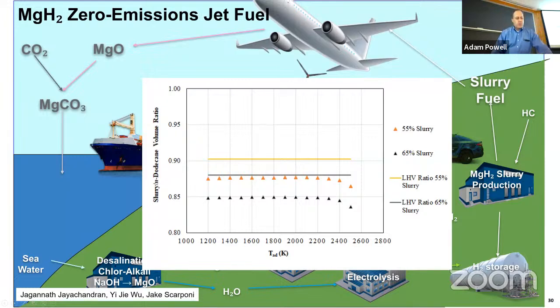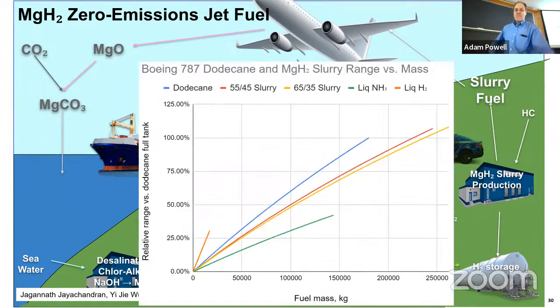And in particular, if you look at the volume, you use much less volume of your slurry, on the order of 15% less. And again, less than you'd predict using the lower heating value based on these complex thermodynamic calculations that Jake and Yijie worked on. It's great. All the students who've been leading these projects are right here today. So it showed us that for aircraft range, volume is more important than mass. Even though this fuel weighs so much more than conventional jet fuel, and dodecane is the simple hydrocarbon that's closest to jet fuel, you end up with 8% more range if you put the same fuel into a 787's fuel tanks, and especially much more range than with ammonia or with hydrogen.